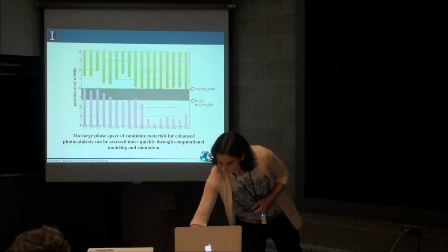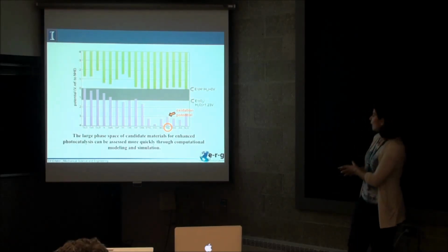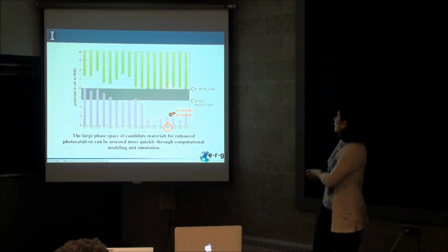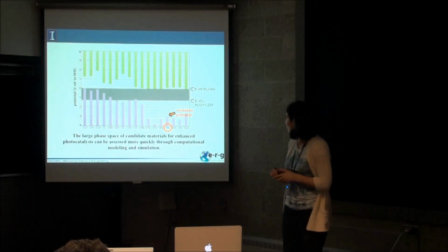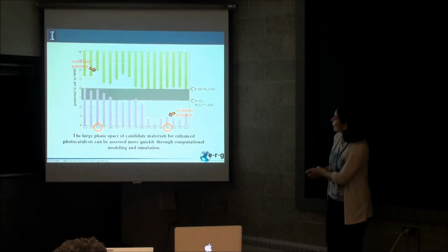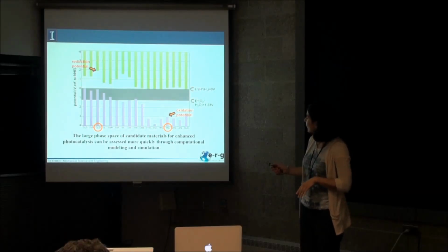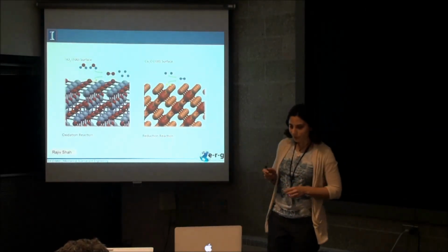And let me point out how we look at this. Okay, TiO2 seems to be a pretty good material for water splitting. And what we can see if we look at the position of the valence and the conduction band edge here is that it has a very low valence band edge, which means that any hole that gets delivered to the surface of TiO2 is going to have sufficient energy to drive the oxidation reaction. TiO2, on the other hand, doesn't have such a nicely positioned conduction band edge to deliver high energy electrons to the surface of the material. So what if we look at this material, cuprous oxide? Cuprous oxide, on the other hand, has a really good reduction potential, a high conduction band edge that can deliver electrons to the surface with enough energy for the reduction reaction to take place. Titanium dioxide, cuprous oxide. Here are our two materials that we're looking at.